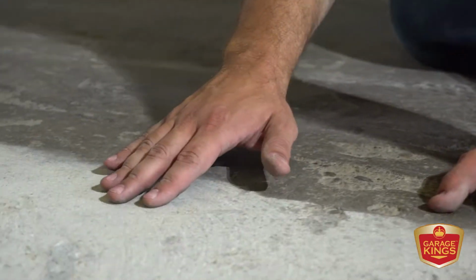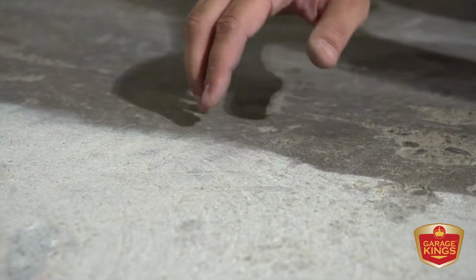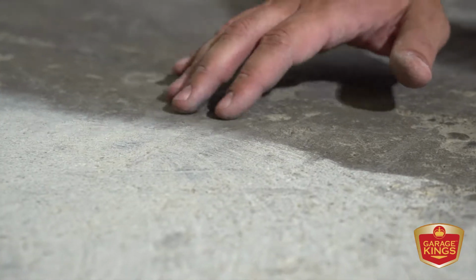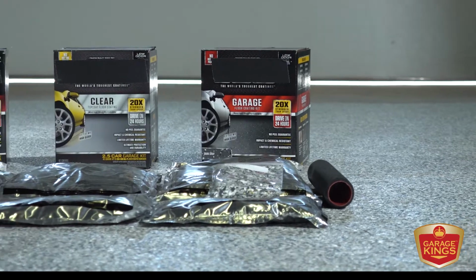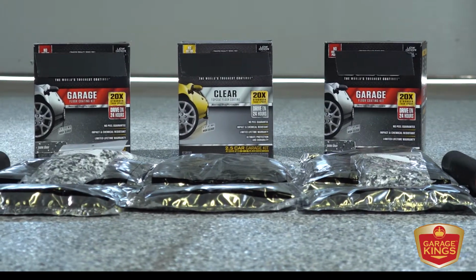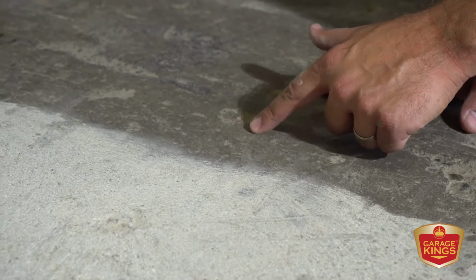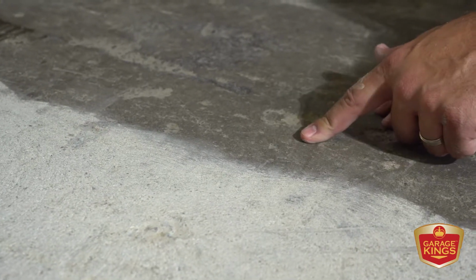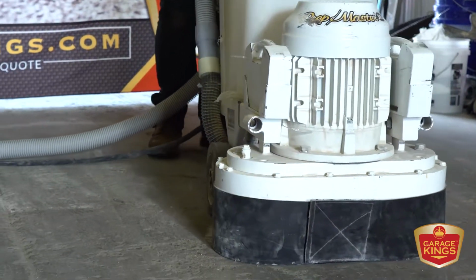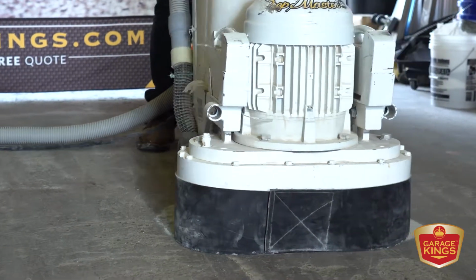This is what I want to show with diamond grinding. What we're seeing here is the difference between diamond grinding, creating surface profile, and doing an acid etch, which is standard with a lot of your DIY or your handyman special type coatings. The diamond grinding is actually cutting through the cream of the concrete, removing the top surface. That opens up the concrete to be more porous, allow the coating to penetrate and bond, but it also leaves a profile behind. We like to use around a 20 grit diamond, and so this has the texture of sandpaper. You can see the swirls and the lines in it from the diamonds that were on the bottom of the grinder.